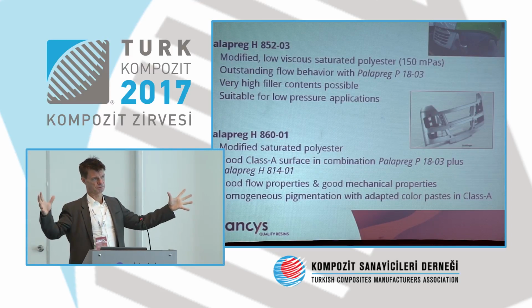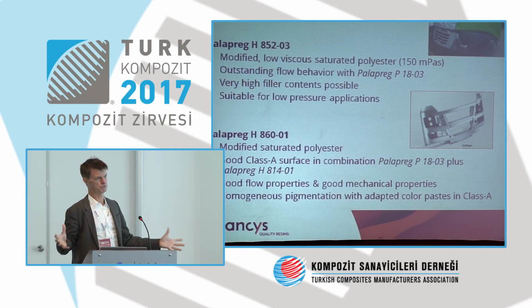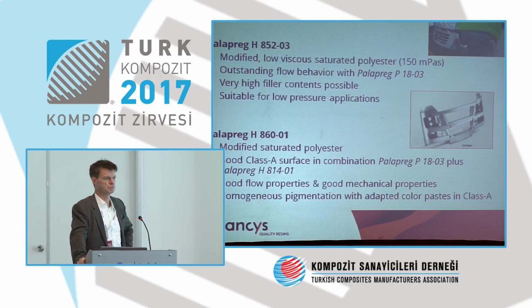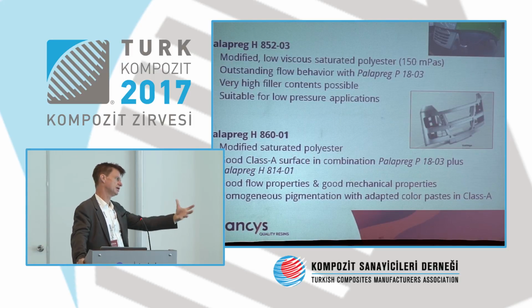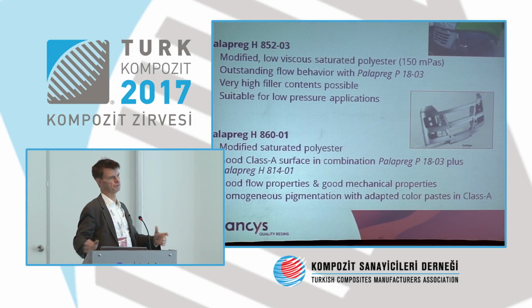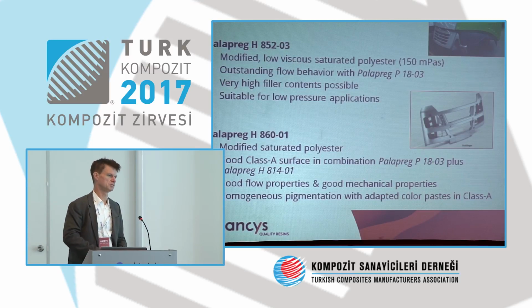Sometimes the molding force on a press is not sufficient, because typically you need 100 bars inside a cavity to mold a part. But if you have a big one, sometimes the capacity of the mold is not sufficient. So it's basically better to develop then a system which is low pressure. And this H852 can be used in low pressure systems. And when I talk about low pressure, I mean 30 bars. About 30 bars instead of 100. But to be honest, if you go slightly higher, it will generate a better result. If you go 35, 40, that should be suitable.